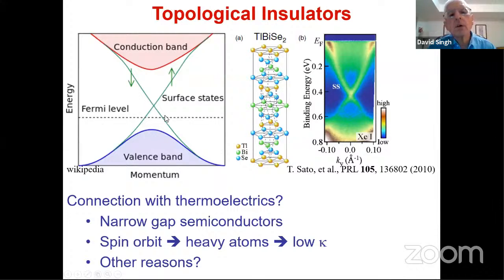And so if your Fermi level crosses those states in the band gap, you can observe those. And so here is some experimental data. But the trouble with that explanation is that for thermoelectrics, the Fermi energy is not here. It crosses either the valence band because we need some holes, or the conduction band because we need some electrons, and we need to optimize that. And we optimize that by having the right number of electrons or holes, not this intrinsic material.